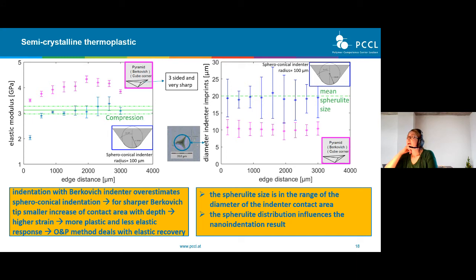On the right side, here we compared the diameter of the indenter imprints. So how big are these imprints from Berkovich and from the spheroconical indenter over the cross section? And we can see here that the size of the imprints is homogeneous all over the sample, but we have bigger imprints, of course, for the spheroconical indenter tip. And the imprints of the spheroconical indenter tip are in the size range of the spherulites. So the spherulite distribution influences the nanoindentation results.